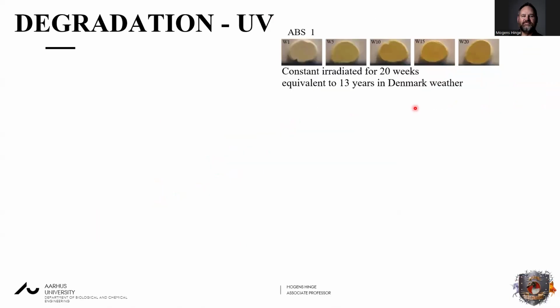Let's move on to the next one, UV. And here again, we have irradiated these for 20 weeks. But please remember that these have been irradiated intensively for 20 weeks. So that means that it's no day or night. So if you take into account that the sun is not shining at night, at least here in Denmark, then this 20 weeks is equivalent to 13 years of UV exposure outside here in our parking lot. So just be aware that when I talk about 20 weeks, it's an accelerated test, which is corresponding to 13